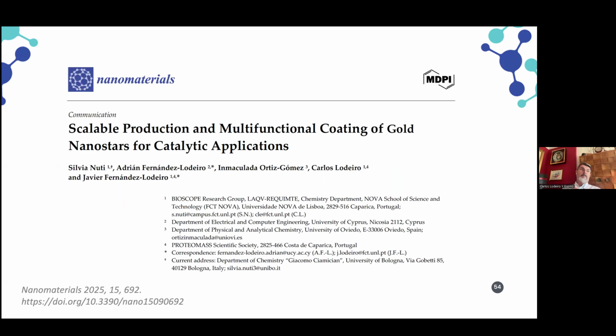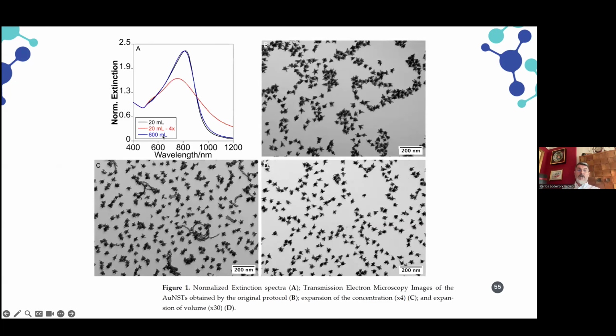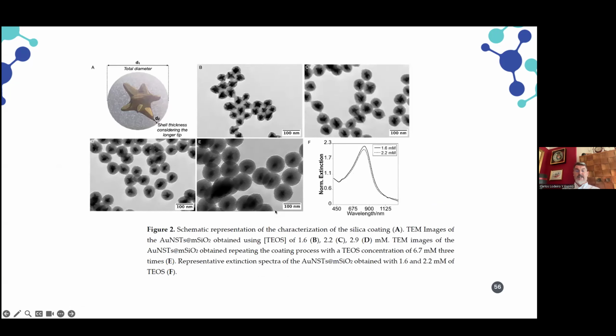Finally, many of our colleagues ask, this is nice, but you are working with very small volumes of solution. So how can we produce this material at scale? Very recently, in collaboration with the University of Oviedo, we are starting to scale up the production of these gold and gold-platinum or gold-palladium nanoparticles. In this case, we can use, for example, up to 1 liter of nanoparticles. We maintain almost exactly the same plasmonic band and the same shape of the materials, and the catalytic effect is exactly the same.